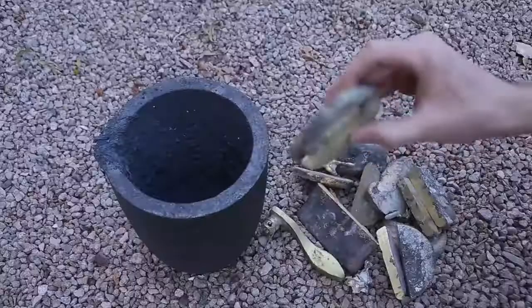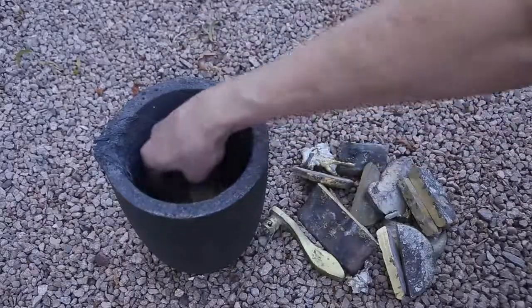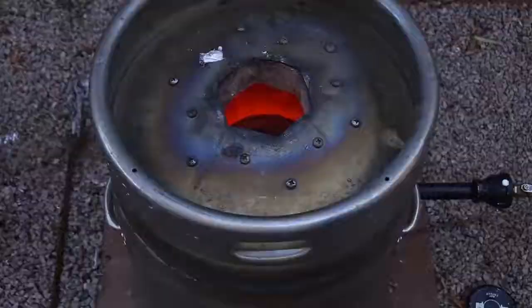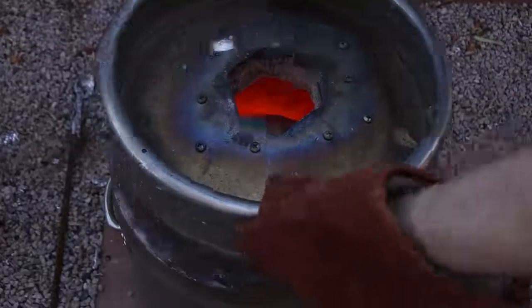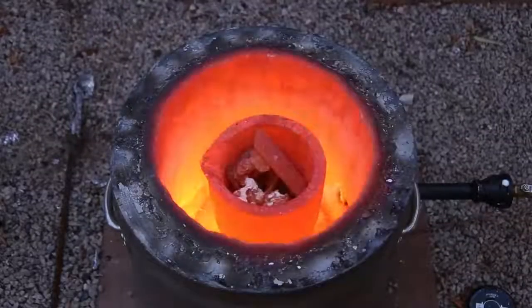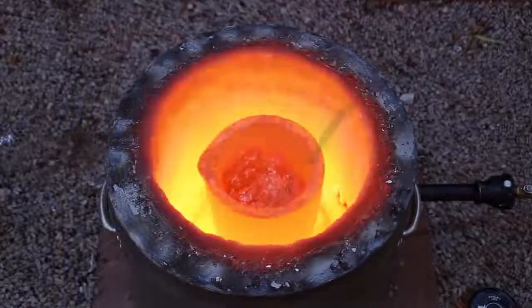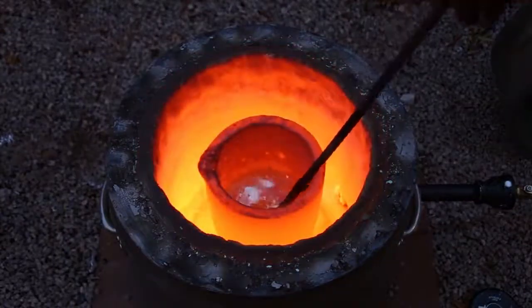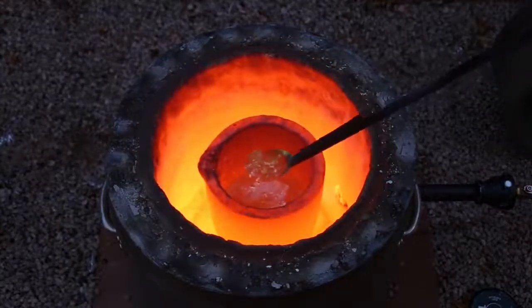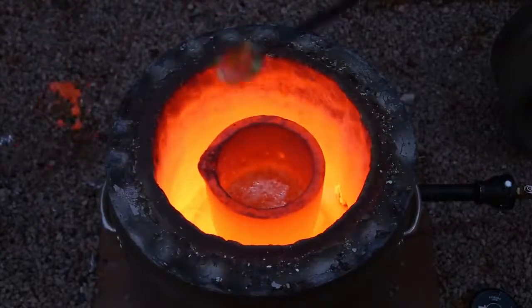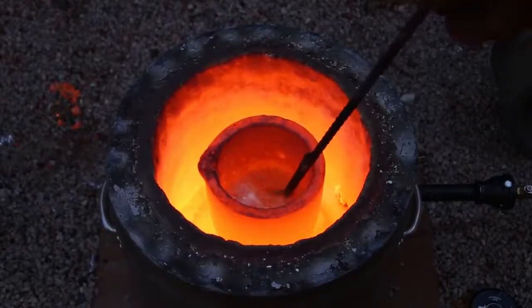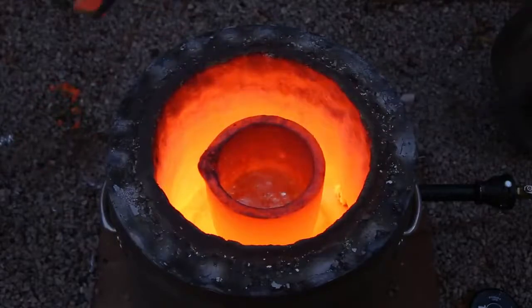After burning out the PLA, I was disappointed to discover that some areas inside the shell had broken away. At this point, I really wasn't confident that the casting would turn out very well, so I decided to fill the mold with brass instead of my more expensive bronze. Brass is similar to bronze, but instead of being made up of copper and tin, brass is made up of copper and zinc, and as a result has a slightly lower melting point of about 1700 degrees Fahrenheit or 900 degrees Celsius.